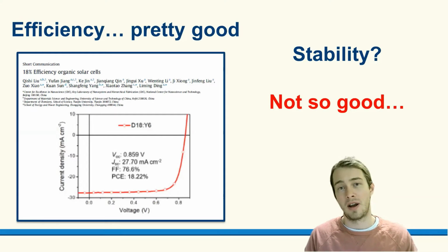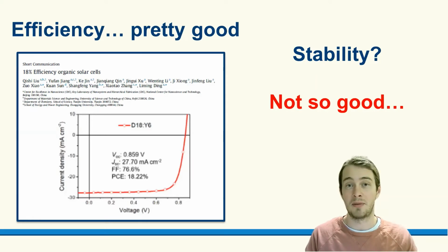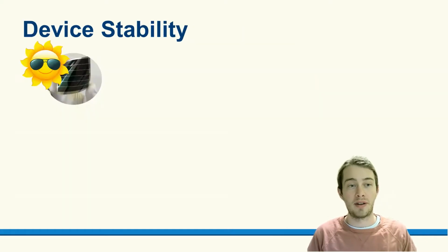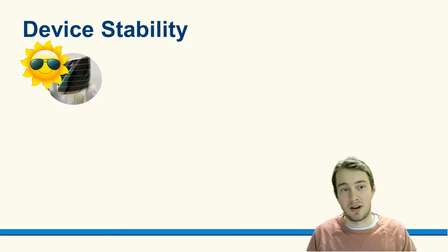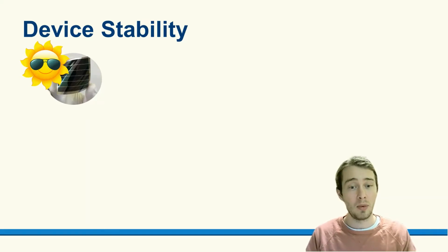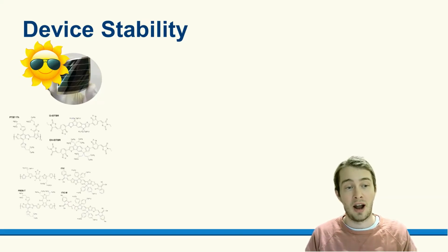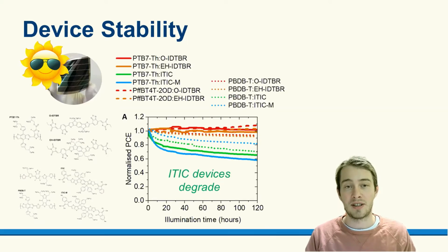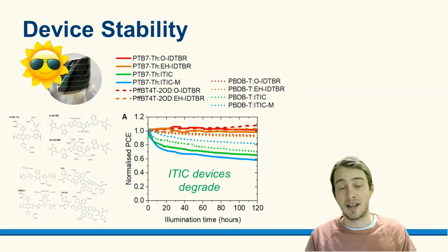So in this paper, I'm interested in trying to improve the stability of some of the materials we use, or at least to understand how they degrade. So the first thing we do is look at the device stability. To do this, we fabricate some devices, then we shine solar irradiation or simulated solar irradiation, and then measure the efficiency as a function of illumination time. And what we did was to make a large range of devices with lots of different materials and two acceptor families, IDTBR and ITIC. And in the devices, we find that the ITIC containing devices degrade quite rapidly compared to the IDTBR.